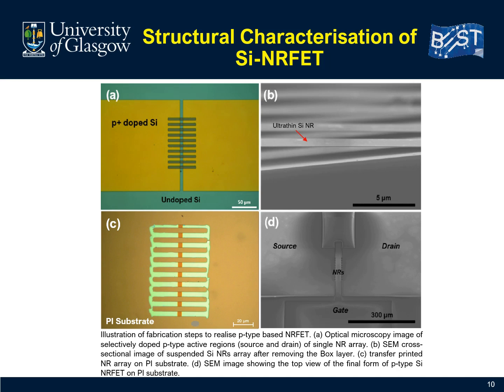nanoribbon arrays before transfer printing on the donor substrate, where the buried oxide, as you can see, the buried oxide layer is silicon oxide underneath the silicon layer, is removed by the etchant solution to form these suspended ribbons. Figure C shows the transfer printed nanoribbon arrays on commercial polyimide substrate, and the final figure shows the final form, the top view SEM of the final form of the silicon nanoribbon transistor.